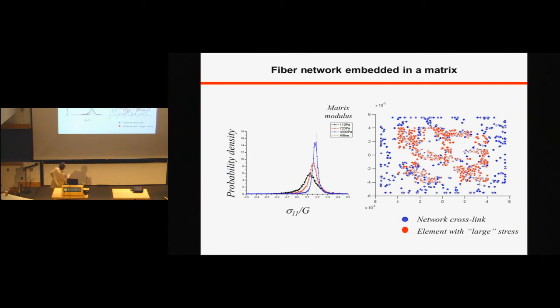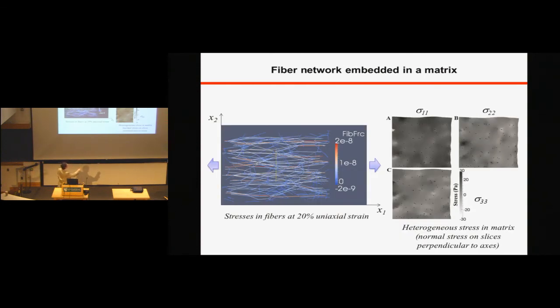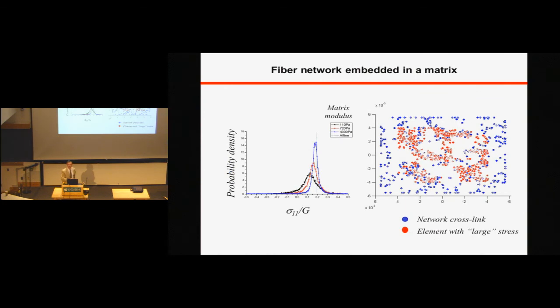Let's try to understand the plot on the left-hand side. We have looked at stresses just in the matrix, okay? And we plot here the probability density function for stresses in the matrix. I'm stretching the network in the horizontal direction just as shown in this plot, right? So I'm stretching it in x1, and I'm plotting sigma 1,1. All right, if you don't have any network embedded, you would expect that the stress sigma 1,1 is whatever you apply in the far field. That is, the PDF, the probability distribution function, is going to be a delta function, which is what this vertical green line is supposed to show. Okay, that's the matrix without network.